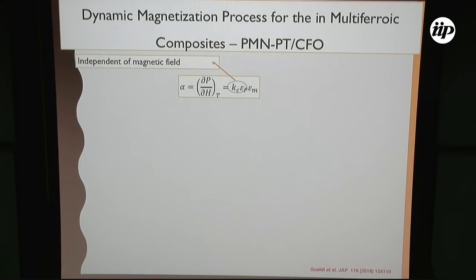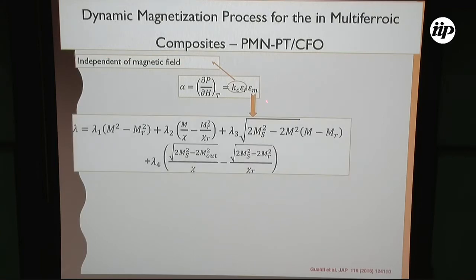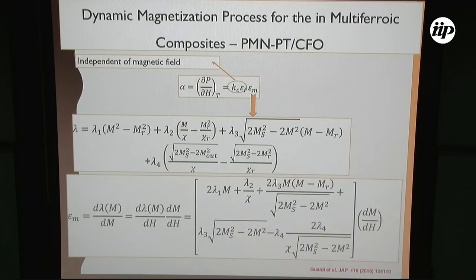So, when observing this expression, these terms, the constants and the polarizations, in principle are not independent of the magnetic field. They depend on the magnetic field. These are the magnetostriction coefficients. When calculating this magnetostriction, there appears a term associated with the deviation of magnetization as a function of the applied field. This is a susceptibility. What is susceptibility? Because when performing the measurement of magnetoelectric fields, an AC field is applied, and the dependence on the frequency is very important.